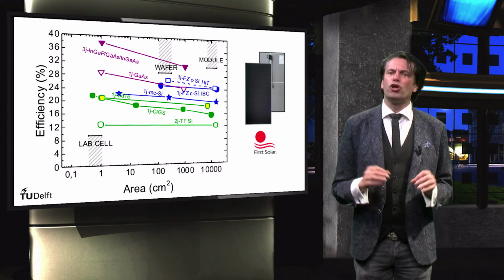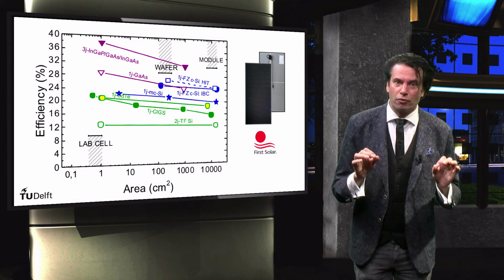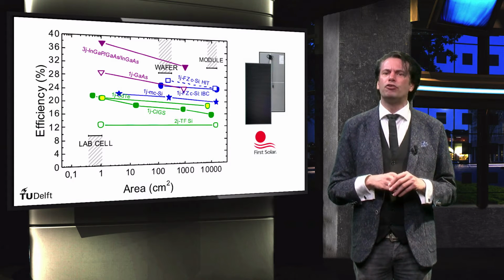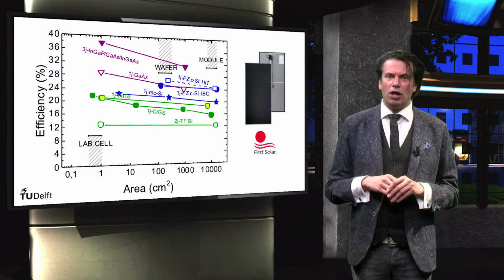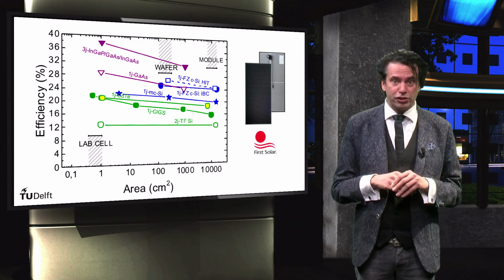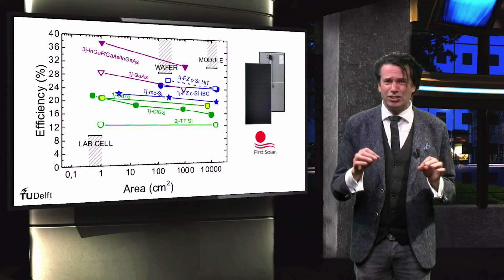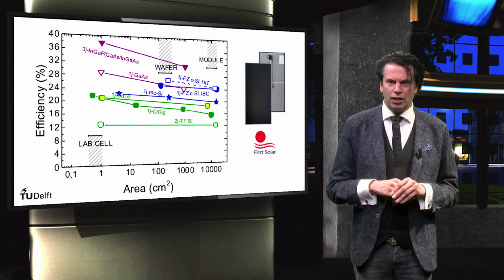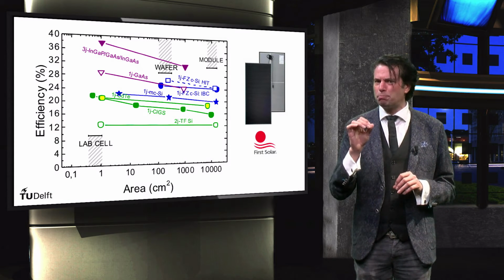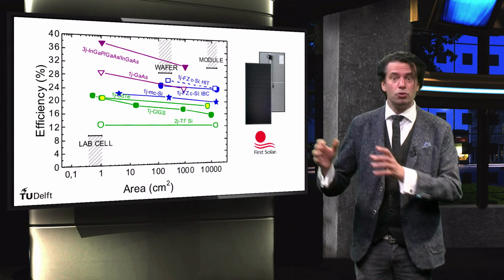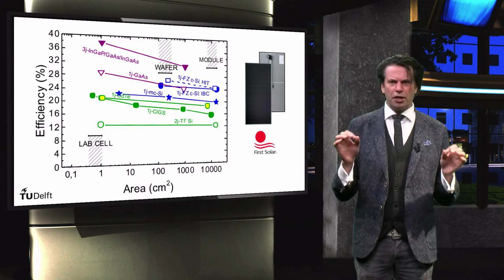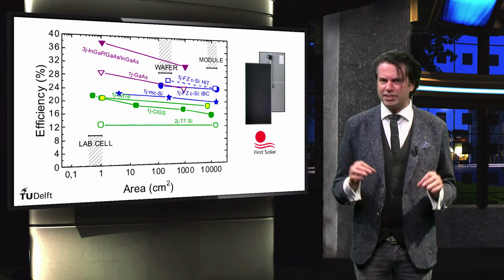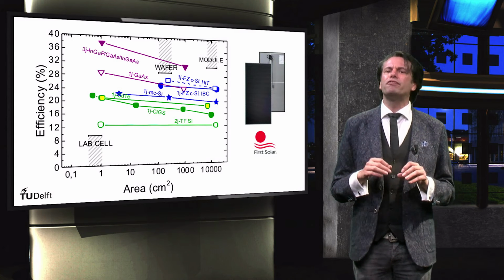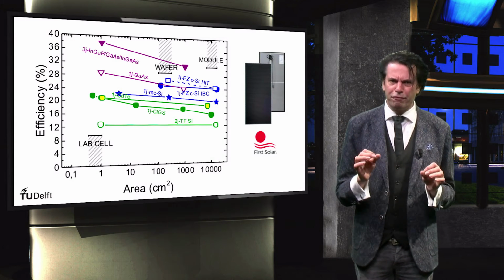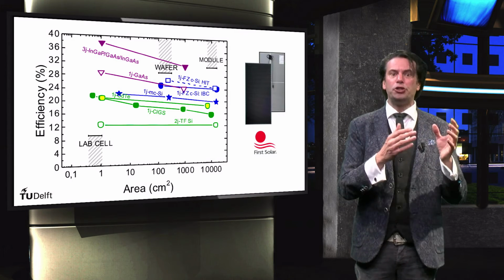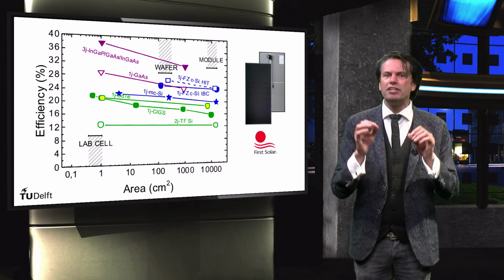The CIGS technology shows a 22.6% record efficiency for a cell of 0.4 square centimeters, while MiaSolé has demonstrated certified module efficiency of 15.7% with a size of almost 1 square meter. This still shows a significant drop of 6.9% of going from cell to module size. An important factor that plays a role is that the various CIGS module manufacturers use different CIGS processing methods. Therefore, the intellectual property needed to reduce the upscaling losses has to be mainly developed in-house.